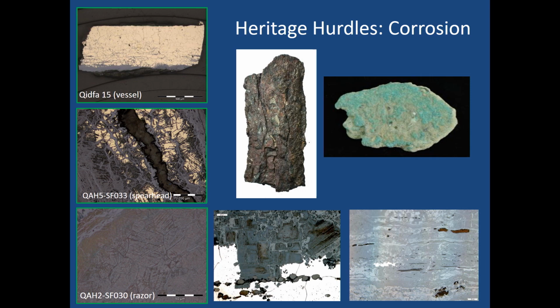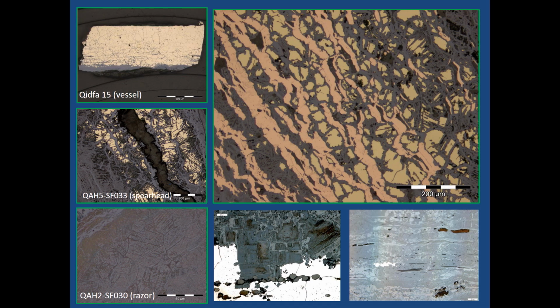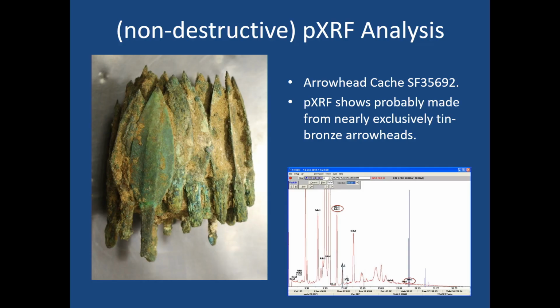It's just corrosion. And it's not just materials being oxidised, it can be wickedly complicated chemical processes happening in the burial environment which can leach out one component of a sample from a copper tin alloy, redeposit pure copper, and corrode the tin out of the sample. So you actually get new compositions being formed over time that never existed in the past. So these are the challenges that we face when we look at this material, and I'll just talk through some of the approaches that have been used.